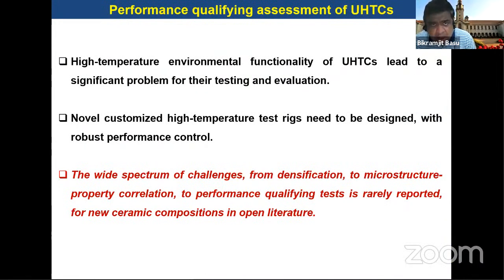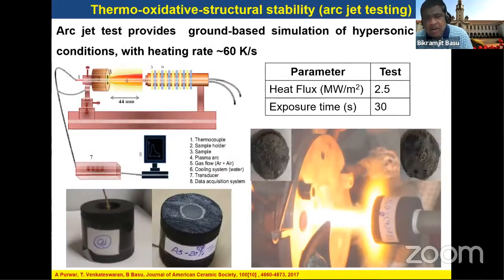Now, coming to the performance qualifying assessment of ultra high temperature ceramics, we have used different types of testing. The first one is arc jet testing. This we have done at the Indian Space Research Organization, at Trivandrum. This arc jet test was carried out with a heat flux of 2.5 megawatt per square meter and with an exposure time of 30 seconds. If you see this, once this arc is heating, this is the material which is exposed, and this is how the material is mounted in the arc jet testing chamber.